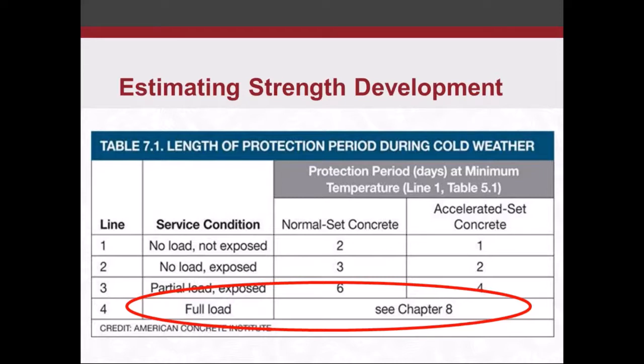Field curing cylinders, which, by the way, we actually field cured cylinders on this Albany project, the pictures I've been showing you. We tuck those cylinders up underneath the blanket so you can't see the cylinders, but that's where they are, and that's where they need to be if you're going to be using field cure cylinders for this purpose.